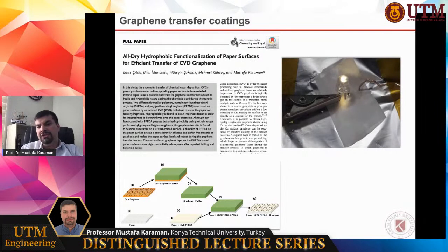In this image, you can see the conductive graphene coatings on the paper surface, which is not possible with any other techniques. But thanks to iCVD, its ultra-dry nature, high functionality, high deposition rates, and low temperature, we could functionalize every surface. In this example, the paper surface. You know, paper is a very fragile material. You cannot use wet coating techniques or high temperature techniques to functionalize paper surfaces, but thanks to iCVD, a low temperature method, we could functionalize the paper surfaces to transfer the graphene. And here you can see the light. The material is conductive at large scales.